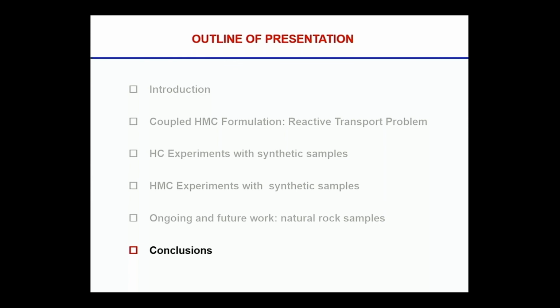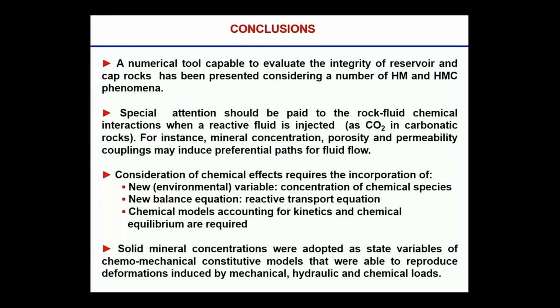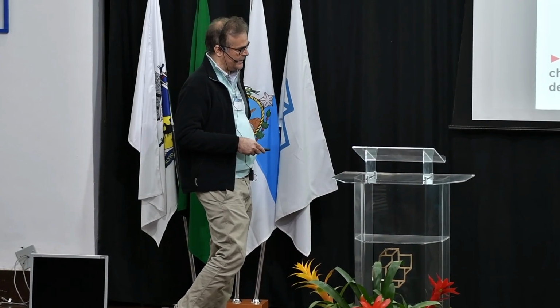And these are the conclusions. I presented a numerical tool capable of evaluating the integrity of reservoirs and cap rocks for a number of hydromechanical and chemical phenomena. Special attention should be paid to the rock-fluid chemical interactions. For instance, mineral concentration, porosity, and permeability couplings may induce preferential paths for fluid flow. Consideration of chemical effects requires incorporation of a new environmental variable, that is the concentration of chemical species, a new balance equation, a reactive transport equation, and a chemical model to account for kinetics and chemical equilibrium are required. And as a state variable for the mechanical problem, we use the solid mineral concentrations, and we were able to reproduce the deformation due to mechanical, hydraulic, and chemical loads.